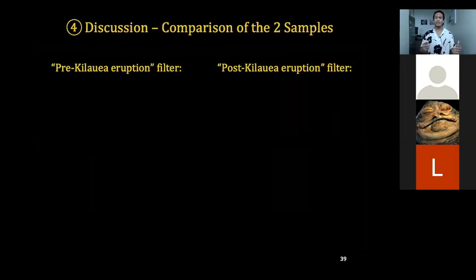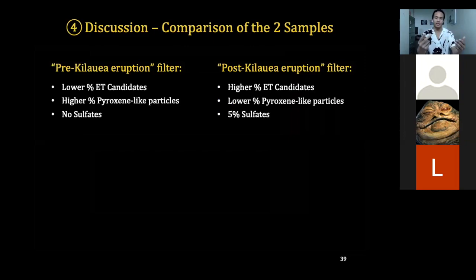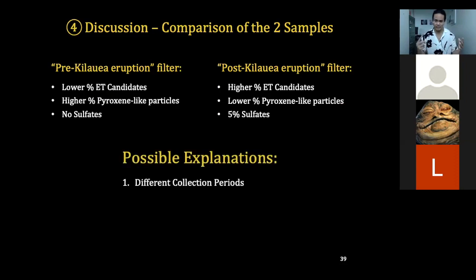So just to discuss those differences a little bit more, again, just as a reminder, I have them listed up above. Lower percentage of ET candidates for pre-Kilauea, higher percentage of pyroxene-like particles, and then no sulfates, and pretty much the opposite for the post-Kilauea. Higher percentage of ET candidates, low percentage of pyroxene-like particles, and then 5% sulfates. So some possible explanations for these differences.